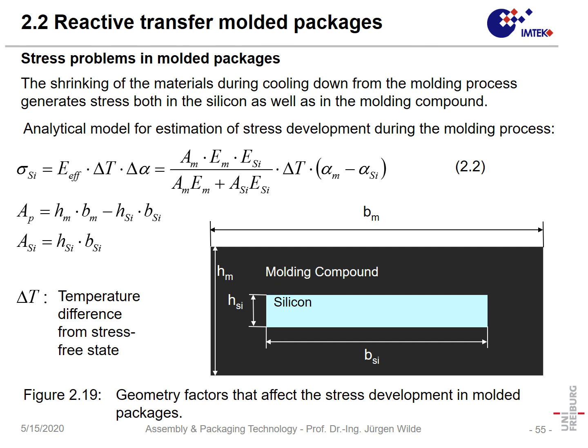Okay, another effect in molding is stress development. Here, let's have a look at a very simple model. We have the silicon here, and that silicon is embedded in the molding compound. And now imagine at 180 degrees centigrade, this molding compound is surrounding the silicon, and now the molding compound solidifies. That leads to a certain shrinkage, but that shrinkage also leads to some stress. But most of the stress comes from cooling down from the molding process. So you could say the stress during solidification is limited, but afterwards the molding compound shrinks.